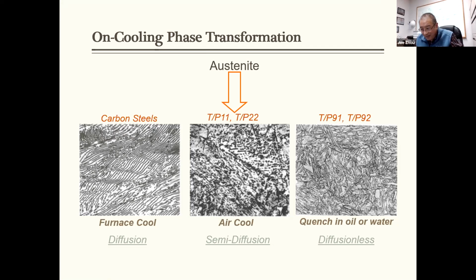Martensite is completely different. When you're forming martensite, it is a supersaturated structure. Nothing comes out. So this is giving a metallurgist a full opportunity by using tempering to control the precipitation behavior. Through alloying, you can add different alloying elements in there. You can control what precipitate is going to form in the matrix, what precipitate is going to form on the grain boundary, and how much you want, and what type of precipitate will form in each different location. So this gives you the optimum control of the material's properties.